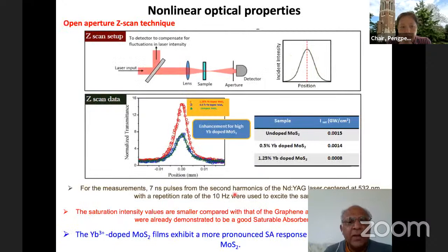Final point, we have compared the saturable absorber intensities using the Z-scan technique, and we have studied these saturable absorption intensities in three different types of materials shown here. Undoped, 0.5% doped, and 1.25% doped. And we find as we increase the ytterbium ion concentration, the saturable absorption intensities are dropping quite dramatically. This is expected to some point because you are creating more excited states, and this may be the reason why such materials could be useful for such applications.